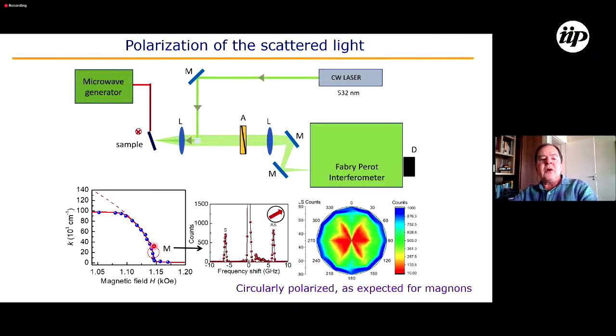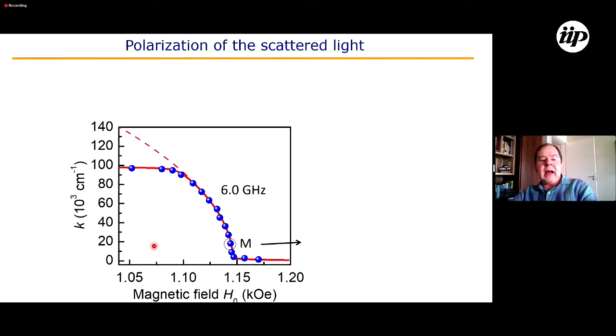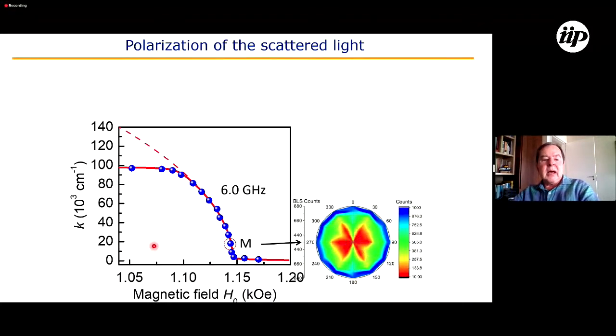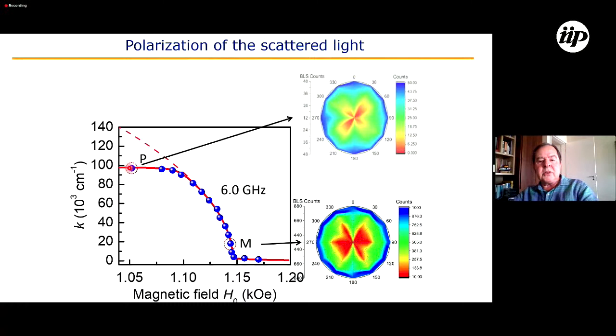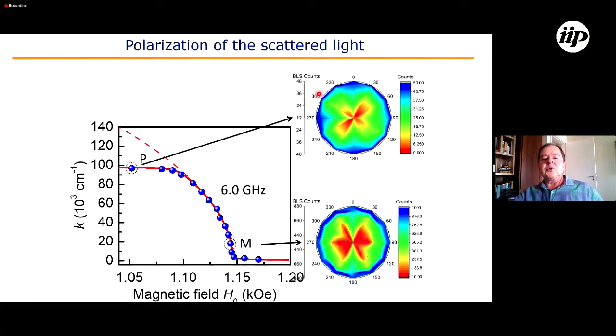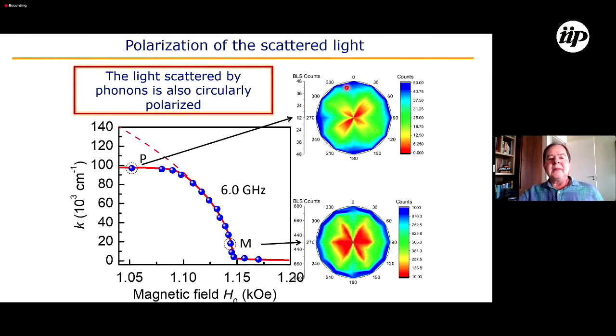So, as expected for magnons. Now if we look in this region here, where we have a phonon, this is a phonon because it's away from the magnetoelastic region, we also measure a circular polarization. This means that the light scattered by phonons is also circularly polarized.